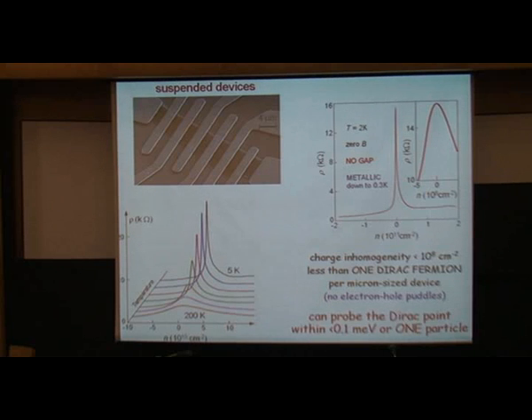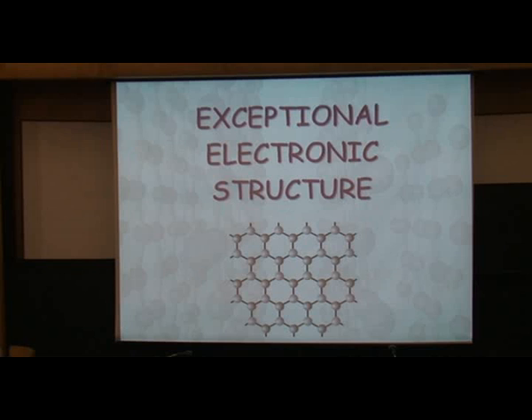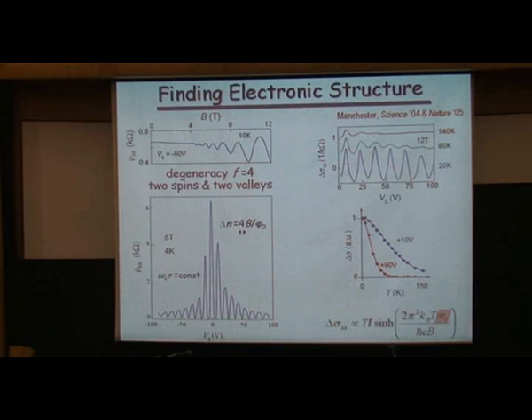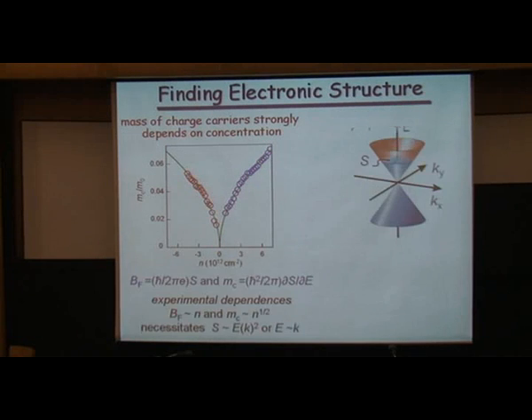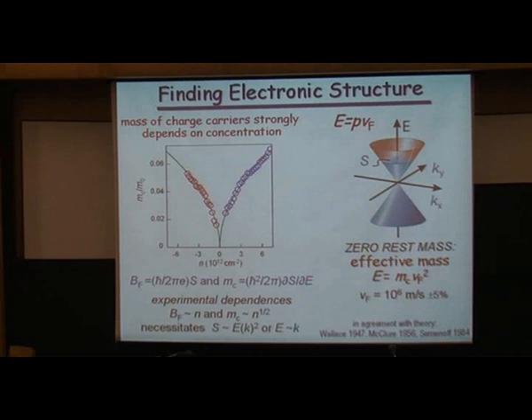So the message from this is that if we have very high quality devices, we can really approach very critical regimes, which I'll describe a little bit later. All these phenomena are essentially due to the structure of graphene, the electronic structure of graphene, which is the next part of my talk. In our first, second and third papers, we started putting these devices in magnetic field and looking at what's happening. We see plenty of oscillations, and from those Shubnikov-de Haas oscillations we can find the effective mass, and from effective mass we can reconstruct the electronic spectrum in graphene. It looks not parabolic as usual, it looks like a linear spectrum, in agreement with theory developed many years before.